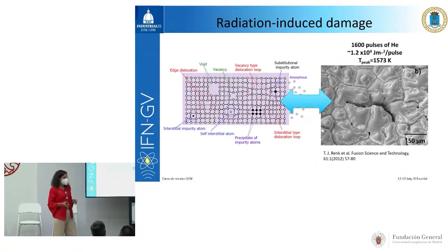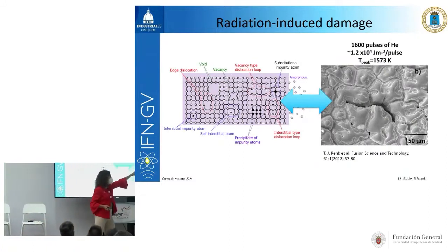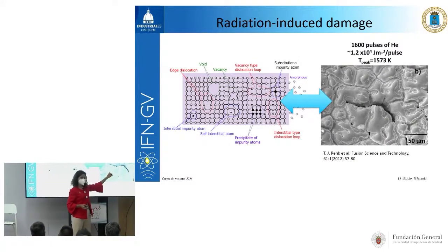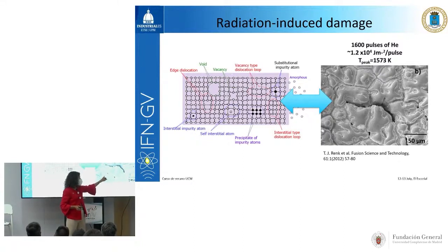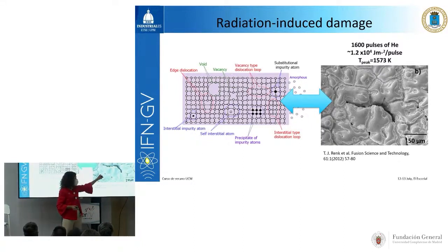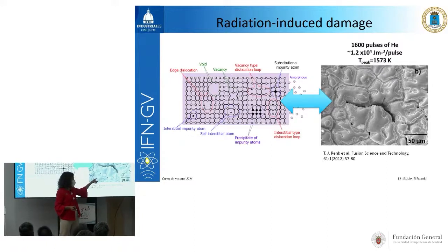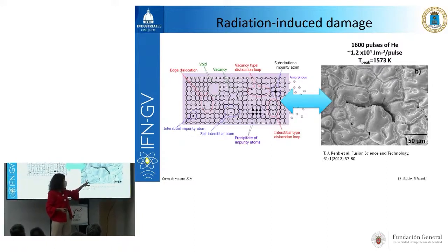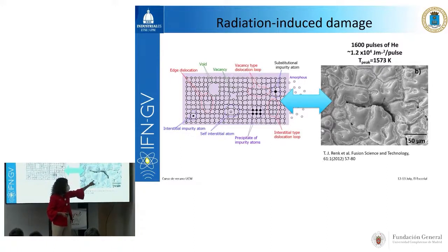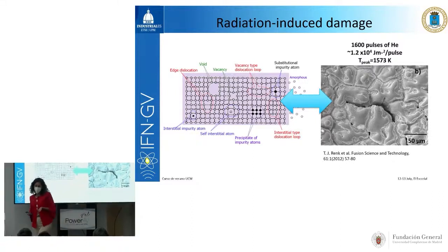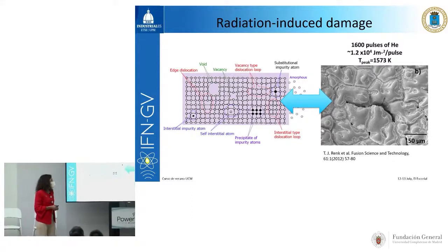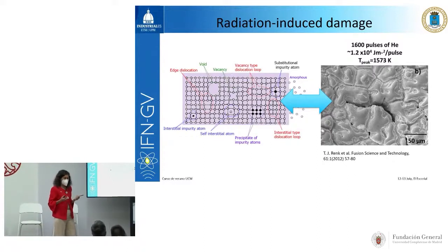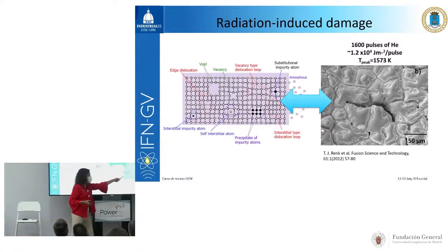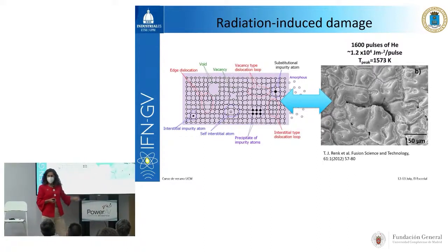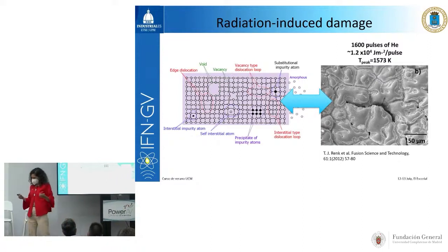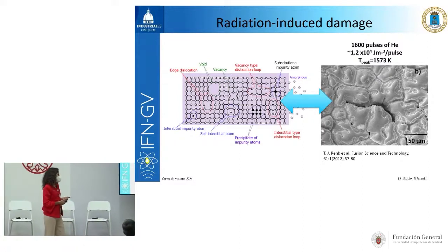So this is what I was explaining to you. Here you may see some bubbles. This is the scanning electron microscopy picture of the tungsten sample after being irradiated with helium in a pulsed way. And you may see here some bubbles, and here you may see that the sample cracked directly. So we need to characterize both. We need to go from here to here and the other way around, and this is why we need different characterization techniques.